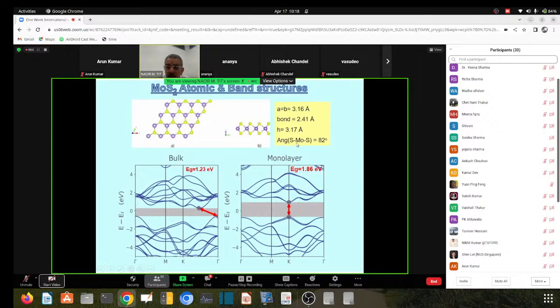The angle between sulfur, molybdenum, and sulfur is 82, and the bulk electronic structure is also shown there. But I am mentioning here the band gap experimental value. The bulk is 1.23 experimentally, but the theoretical band structure looks like this. It's an indirect band gap, whereas the monolayer has a direct band gap at the K corner with the value of 1.86 experimentally. Okay, then I move on.